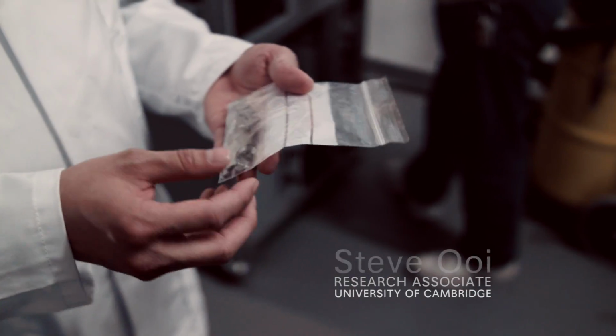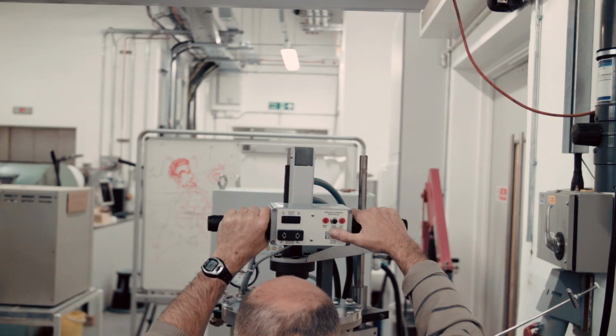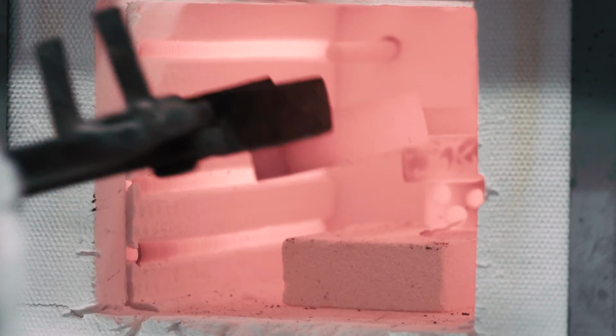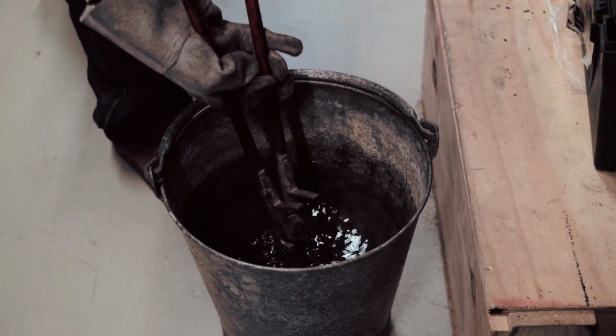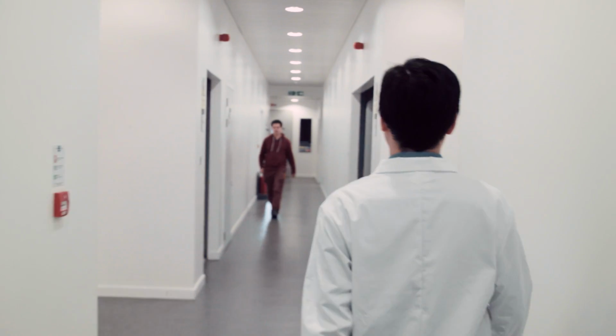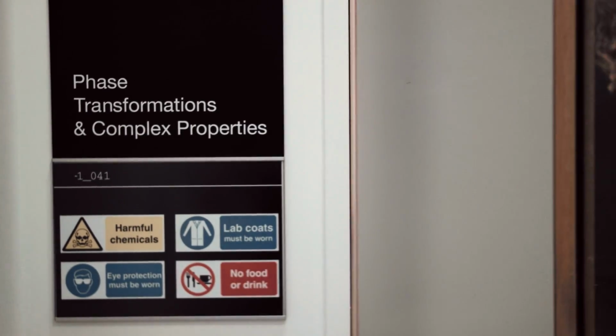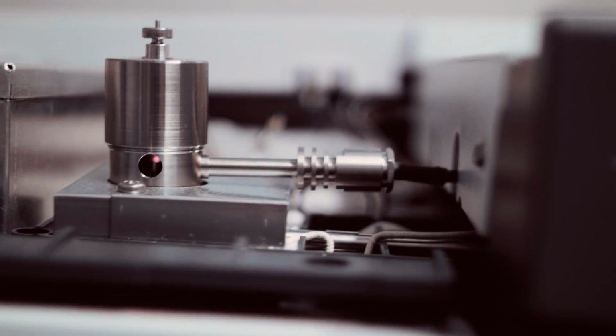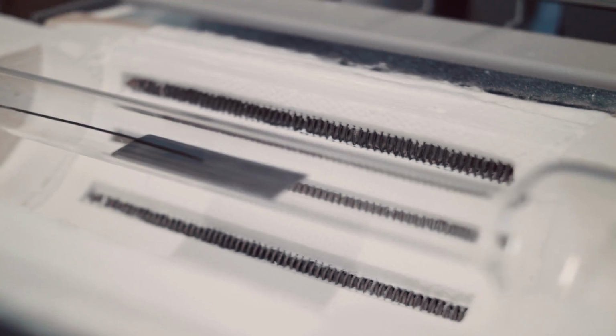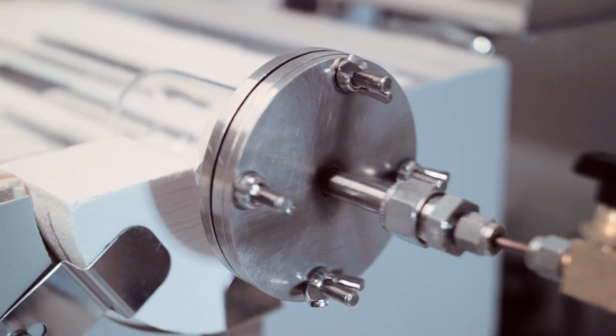What I got here is a mixture of pure elements. What Kelvin is doing now is melting all these elements together and mixing it all up. We're going to perform a heat treatment and then we cut it all up. One piece is to go for chemical composition measurement, the other to measure the hardness. This equipment will separate out the hydrogen, oxygen and nitrogen, and then we can measure the amount of hydrogen inside the steel.